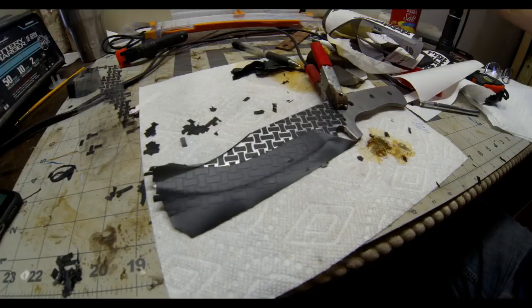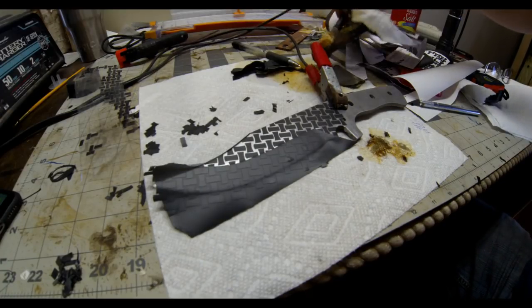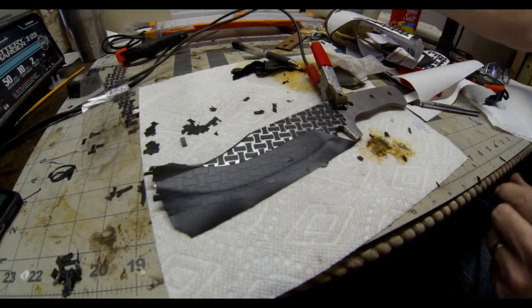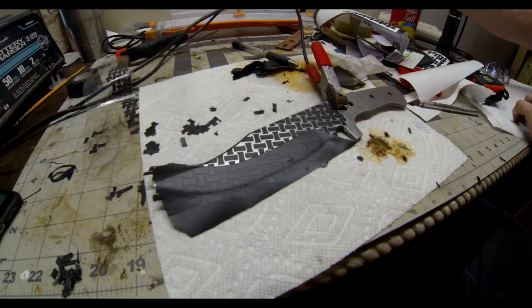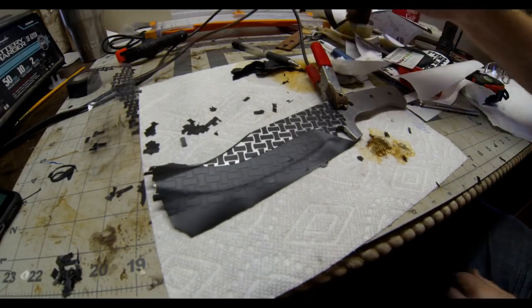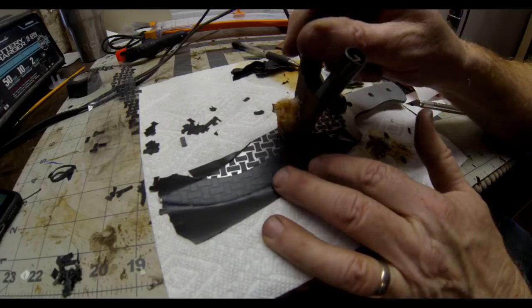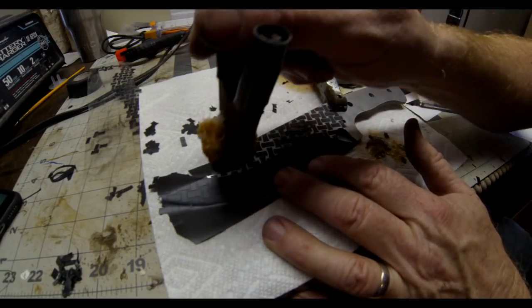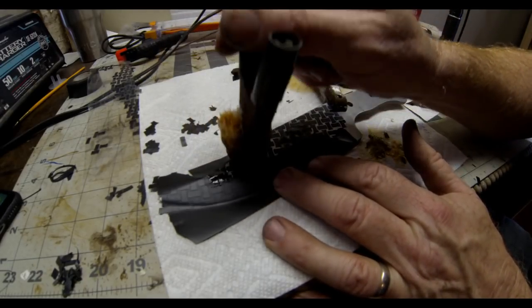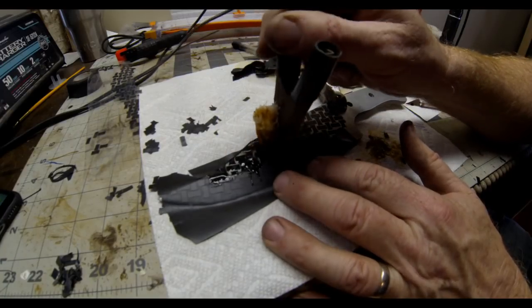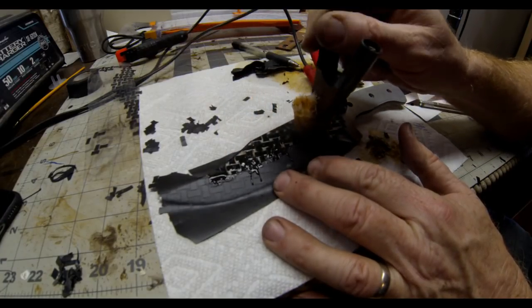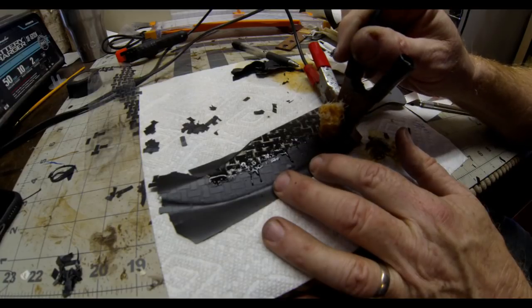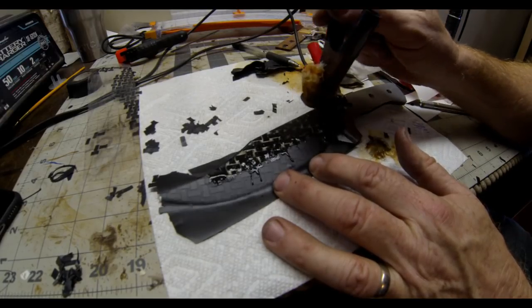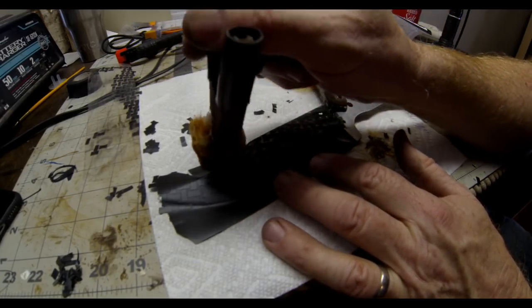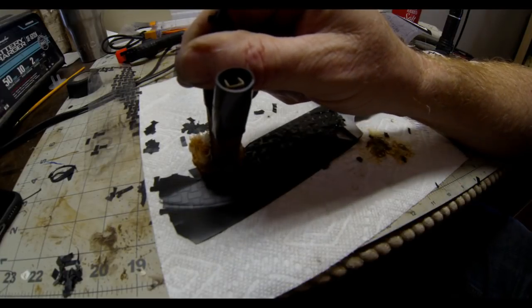And then my preferred method of metal etching is using a car battery charger, a 12-volt charger set at 2 amps. I connect the positive lead to the blade, and the negative lead I clamp to a gauze pad that's kind of folded up, and I dip that into a salt water solution as the electrolyte.